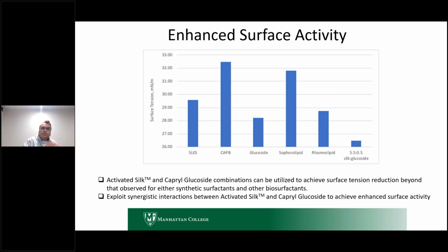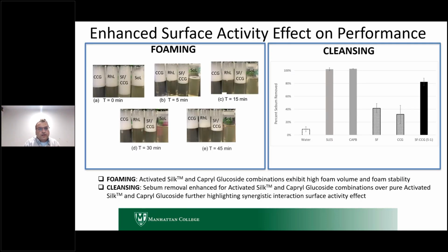So that was a big optimization exercise of playing around with all the different ratios, electrostatic interactions, and then we came up with this magic ratio, if you will, of silk to glucoside, where we optimized and minimized the surface tension of the system. Also, I'm not showing it here, but we also enhanced the surface elasticity of the system, and you can see what it does here in terms of the foaming, right? So here again, the second from the right, the SFCCG sample, is the one we have optimized for its surface tension and surface activity. And we compare it with the other samples you were seeing there.